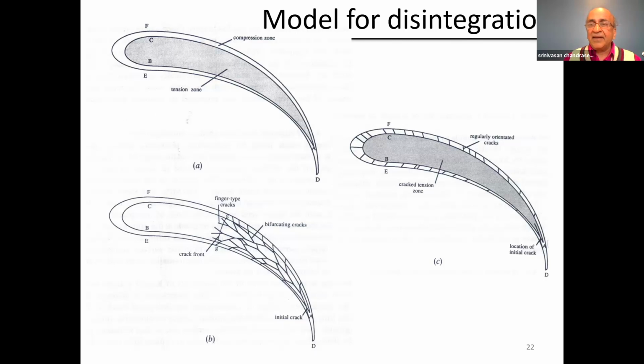So you start a crack, it picks up speed from the energy stored in the tensile zone, and reaches the threshold velocity at which it finds it's easier to propagate by bifurcating. Each of these bifurcated cracks then picks up speed, and the process repeats continuously. We saw the evidence for the bifurcation from the fingers ahead of the crack tip. So this is the reconstruction we could do based on the experimental evidence of the cracks hitting a threshold speed and then seeing evidence of the bifurcation.